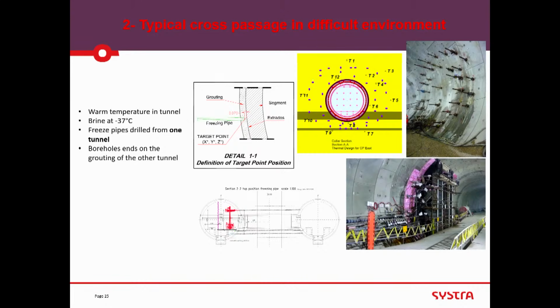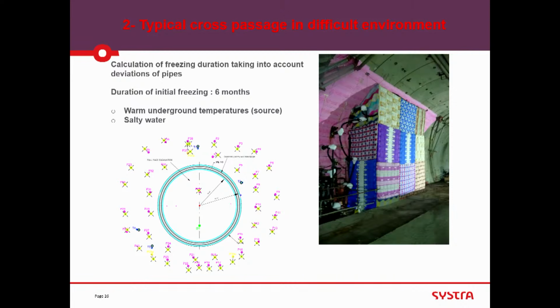And by back calculation, now I'm pushing a little bit of calculation, the measurements were very different from what was expected in terms of temperature. Very different. We had to investigate, and in fact, we even had to reinforce the energy in this area for freezing the contact. How did we do it? So these are the freezing pipes, as you can see.